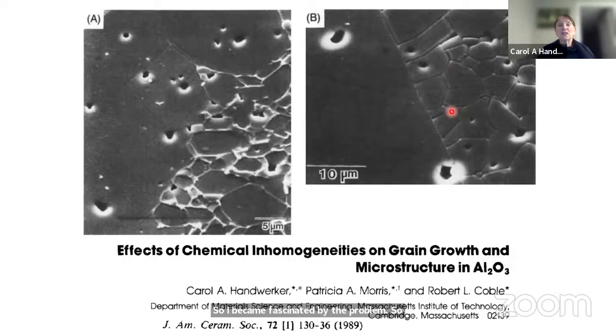And that is, the microstructures are evolving in the ways on the top right-hand side, but then all of a sudden, something changes in the microstructure. Something has gone out of local equilibrium such that a few grains begin to grow at the expense of all the others. So the driving forces here have changed. And so these can be one grain out of 10,000, 100,000 grains. So I've been working on these kinds of problems my whole life.